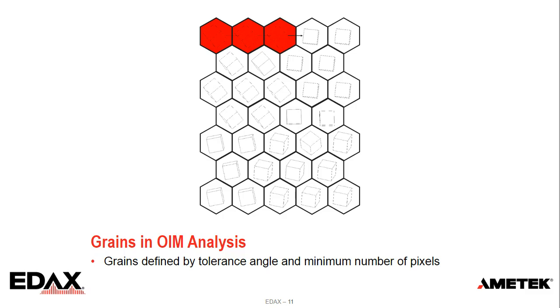And I just want to point out here, our default tolerance angle is 5 degrees. So if the misorientation between the first and second pixel is, we'll say 4 degrees to keep it round, and if the misorientation between the second and third pixel is 4 degrees, the misorientation between the first and third is then, of course, 8 degrees. So you can get a lot of grain orientation spread within a particular grain, even if the misorientations between points are lower. And we'll see some examples of that a little bit later.